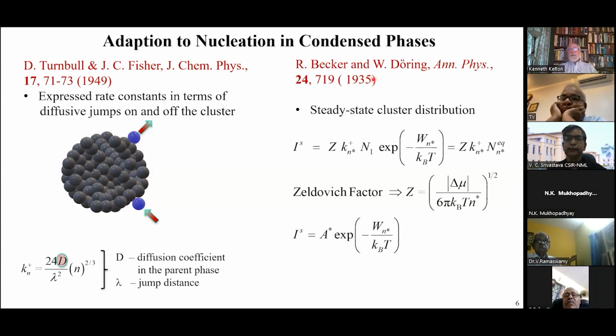They then used an expression that had been derived by Becker and Doering earlier in 1935, where they looked at the question of what is the correct distribution to describe the nucleation rate, and they argued that it's a steady state cluster distribution, from which they could get the steady state nucleation rate in terms of a factor Z, which is the Zeldovich factor, which is shown here, and it typically is between 0.1 and 0.01.